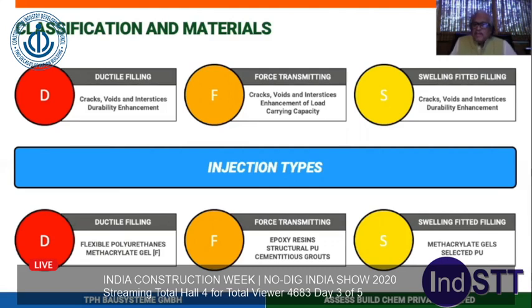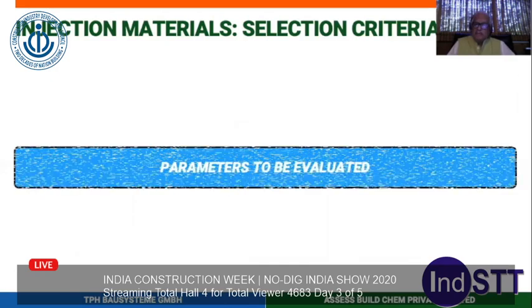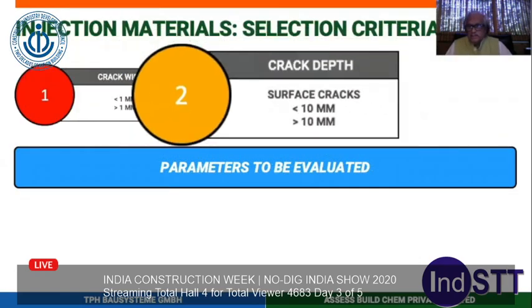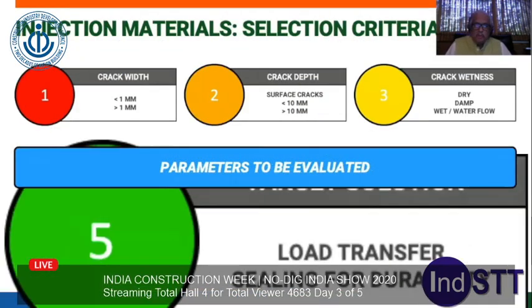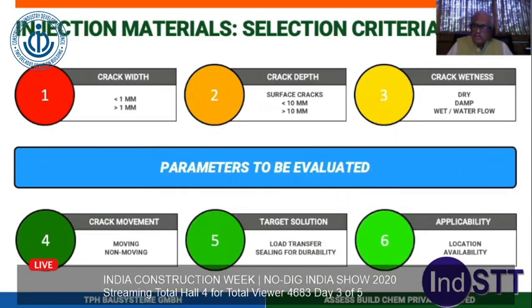And finally, for the filling, you can also use the foamed materials, which are either gels or silicate foams or polyurethane foams. So a large gamut of materials are available, but these are to be selected depending upon very few important things, which is the crack width, because crack width will determine the viscosity. Crack depth will also determine the viscosity, how deep you want the material to penetrate.